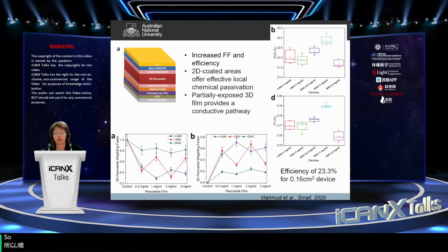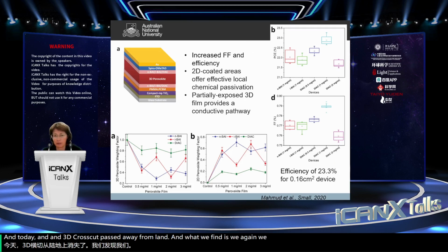We then did some related work using a mixture of 3D and 2D perovskites. This is interesting because it was quite a different approach, but in the end, the mechanism is quite similar. Here we've got a mixture of butyl ammonium iodide and a 2D and 3D perovskite passivation layer. What we find is we get an increased fill factor and efficiency. The 2D coated areas give you effective local chemical passivation, but of course they don't conduct so well. But you also have the 3D film, which is partly exposed, providing the conductive pathway.